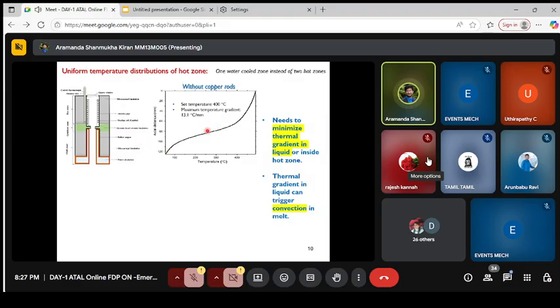The issue here is that the gradient needs to be better, and inside the hot zone there is a slope here. We don't want that to be a slope, we want it to be straight, because if you have a change in temperature from 500 to 400 inside the hot zone, that leads to a thermal gradient in the liquid, because we keep the sample in the liquid state in the top zone. When there is a thermal gradient in the liquid, that can also cause convection inside the liquid, and that convection will again change the microstructure or the structure inside the material, and that leads to a different type of material than expected.